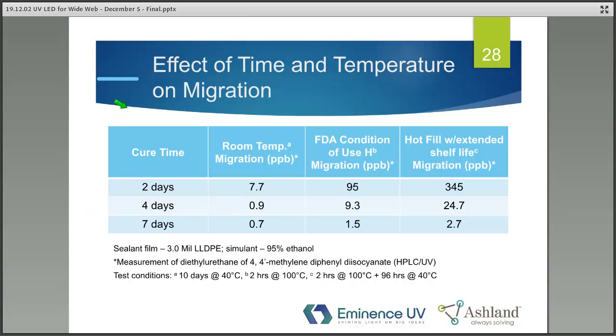So again, this is an aromatic isocyanate migration from a laminating adhesive on a 3 mil linear low density barrier film. All this testing was done in 95% ethanol, so this is a fatty food condition, so I want to keep the conditions the same. You see at room temperature, there's less migration, but as you go to FDA condition of use H, so this is your kind of frozen burrito application where you have a refrigerated or frozen food and you throw it in the microwave, you can see migration increases.